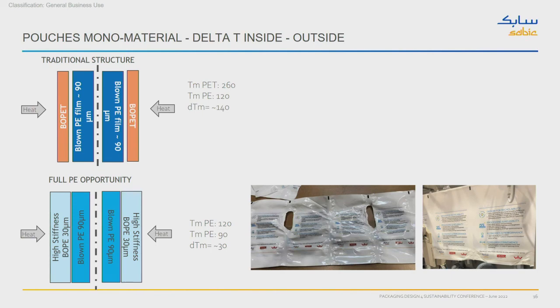What is the problem? I think it's very simple. If you look at the melting point of polyester, roughly 260 degrees, polyethylene on the inside, 120 degrees. So you have a delta T in melting temperature between outside of the film versus inside of the film of, give or take a few degrees, 140 degrees. So your packaging process from that point of view is relatively robust. You can more or less do whatever you want.